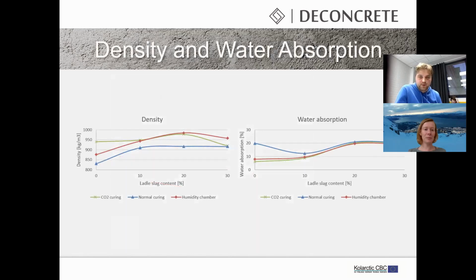And here are the density and water absorption of the granules. The limit for lightweight aggregates is like 1,200, so all of them are below that limit, and so they can be classified as lightweight aggregates, which is a good thing. Also, water absorption behaves quite inversely compared to the density. I think the water absorption of those commercial aggregates was something about 20%, so they are mostly below or similar to that. So the properties are quite comparable.